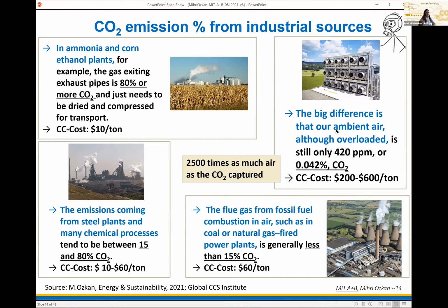If we do all this with direct air capture, we have to go down in the pressure all the way to 420 parts per million. So this is a very low carbon dioxide partial pressure, and because of that, the cost is high. We go up to $200 to $600 per ton of capturing carbon. If we compare DAC versus the flue gas, since the pressure is different, we need to pass about 2,500 times more air to capture the same amount of carbon dioxide in the case of DAC.